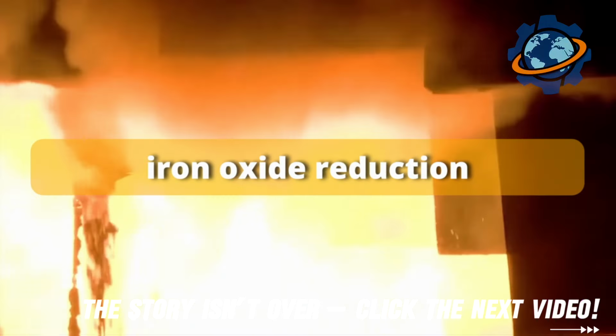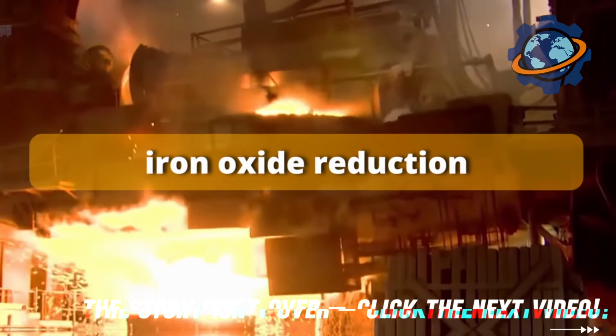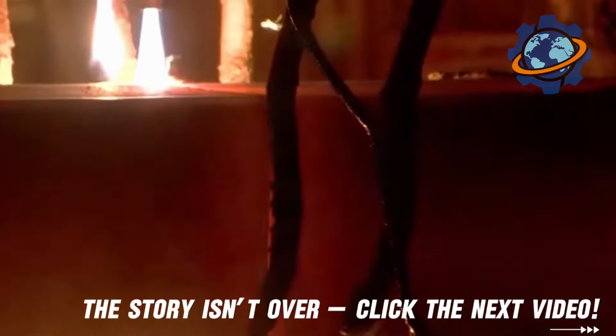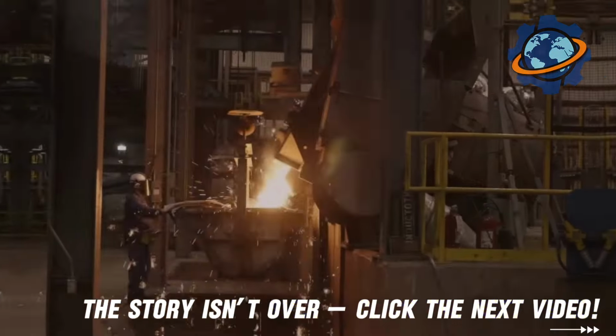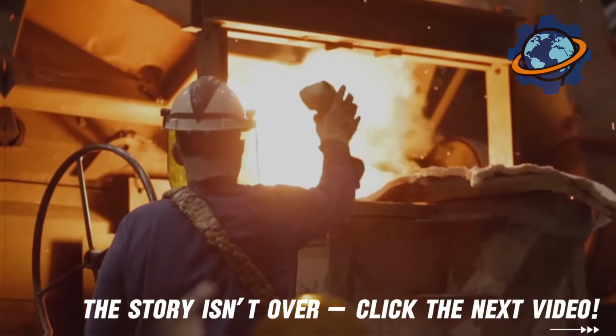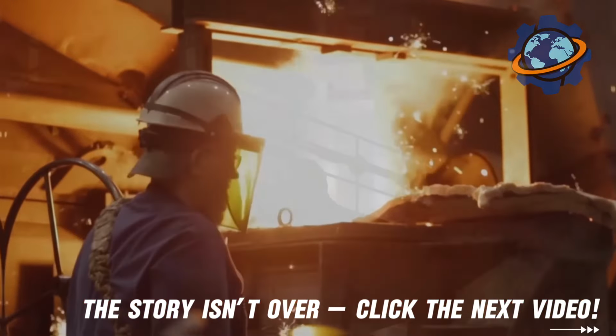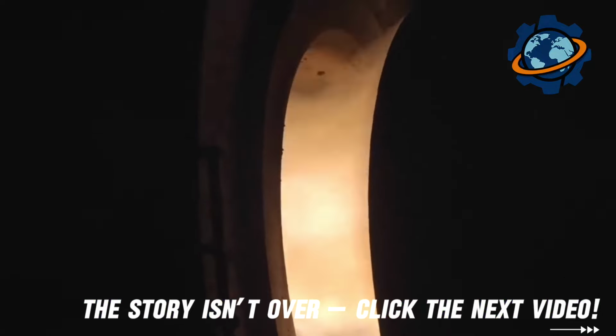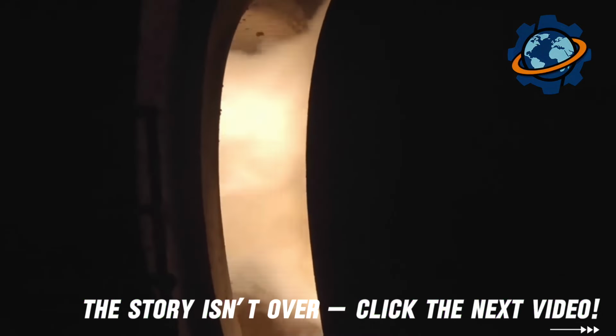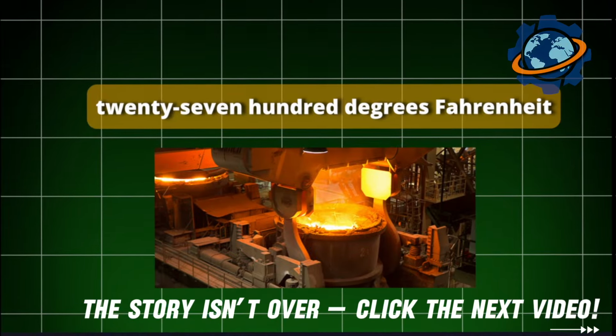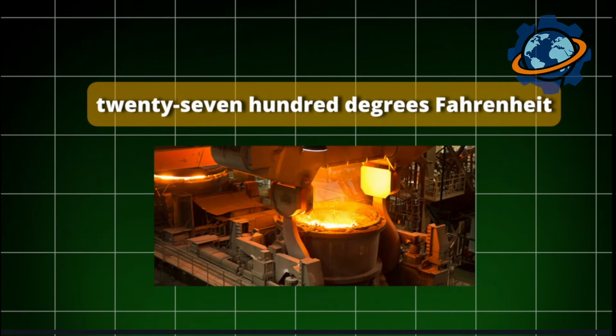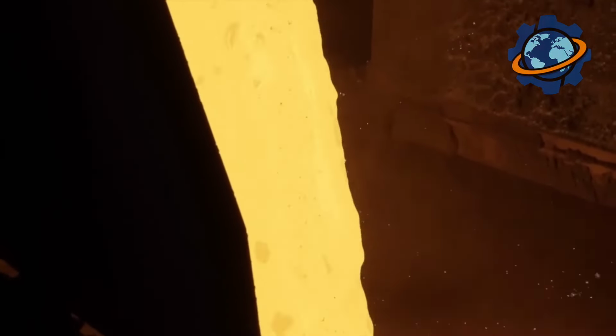Then, at 930 degrees, iron oxide reduction begins. Carbon from coke strips away oxygen. At 1800 degrees, ore becomes spongy iron. At 2700 degrees, iron melts. Drops of molten metal flow down. At the furnace bottom, molten pig iron accumulates, an iron alloy with 4% carbon. Pig iron temperature at the furnace bottom is 2,700 degrees Fahrenheit. It glows blindingly white with an orange tint.